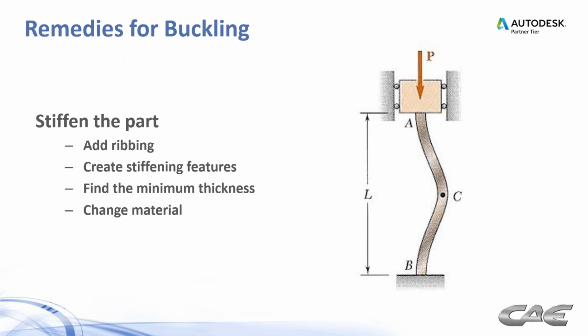Sometimes it's a change in material. That's a more difficult thing to do. Typically you're so far along in a project that the material is the material that's going to be used, and that's that. But I have seen cases where parts have buckled, and we've changed the material to get rid of that buckling, and that was acceptable. But this is one of those cases where you would have to do this very early on in a project, and this is what we preach all the time, right? Do mold flow early. If you're doing mold flow early, you can catch these problems, and you have a lot more solutions open to you to fix a problem than you do when you're getting ready to cut steel on the mold, for example.